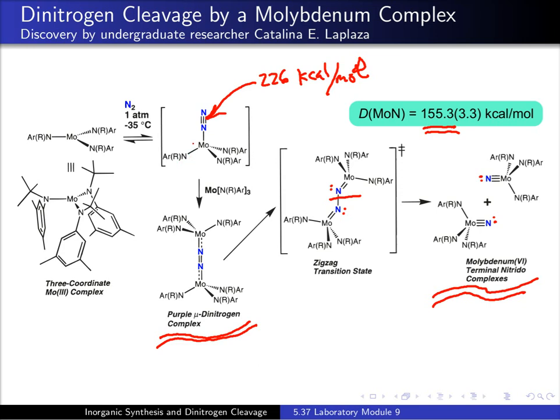But then, when it was discovered that this complex not only binds the N2 molecule but is able to completely split it apart, that opened the possibility for using an N2 splitting reaction involving homogeneous complexes as the basis for fixing nitrogen using synthetic coordination complexes, and to do so in a way that involves a nitrogen cleavage reaction as the important first step in that process.